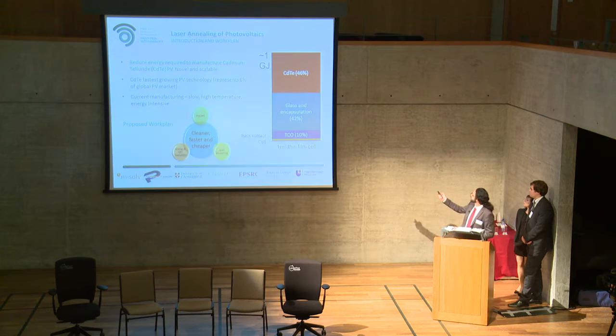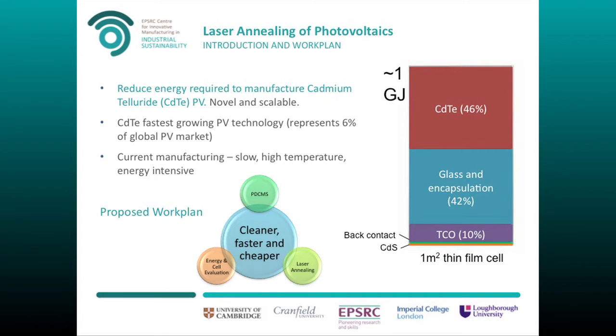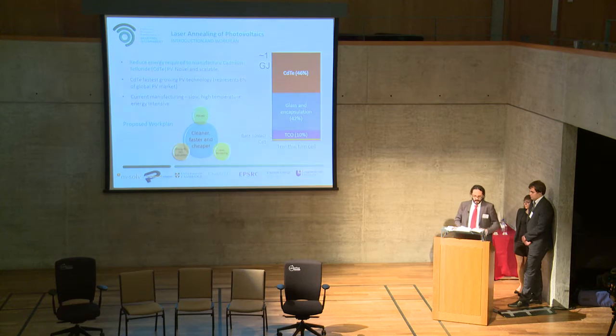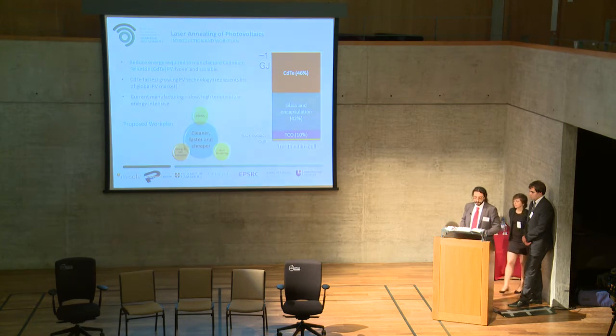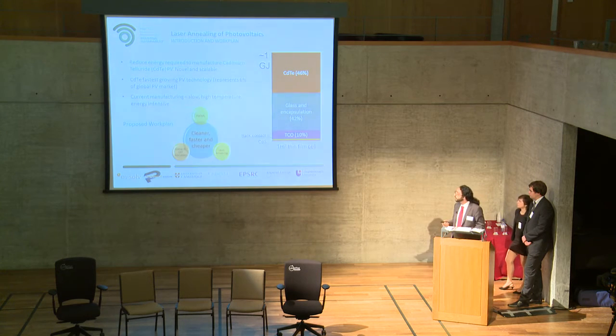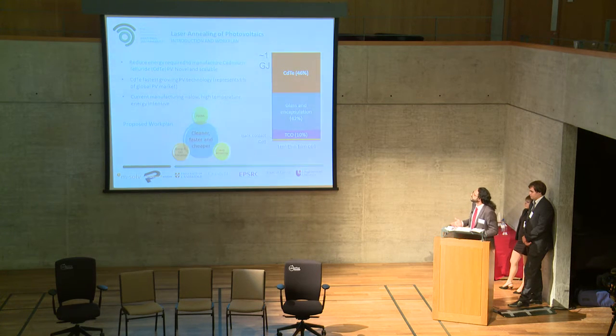1 gigajoule, but 46% of this enormous amount of energy is represented by the cadmium telluride layer, which is an extremely thin layer, 2 microns over a total thickness of 6 millimeters. Well, cadmium telluride is a growing market, and represents currently 6% of the global PV market. But the drawbacks are that the process is slow, requires very high temperature, and is very energy intensive.